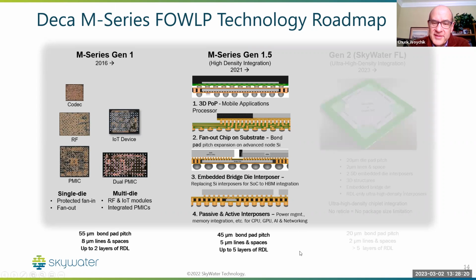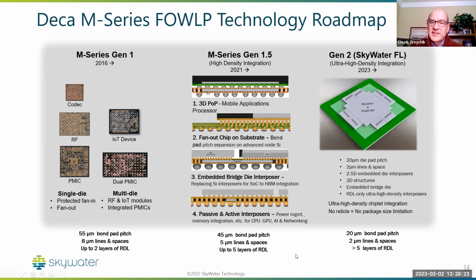But what we want to do is get into the next, which is a Gen 2. And this is where we bring up this technology at SkyWater in Florida. And the exciting thing here is this is the state-of-the-art DECA M series, which gets into a 20 micron bond pad pitch with 2 micron lines and spaces. And we believe we can go greater than 5 layers of RDL on the surface. So the beauty of this is, as you can see, the ultra high density integration. And this is a technology we're aiming to get up and running in the late 2023, most likely 2024 timeframe, to have that capability up at SkyWater in Kissimmee, Florida.